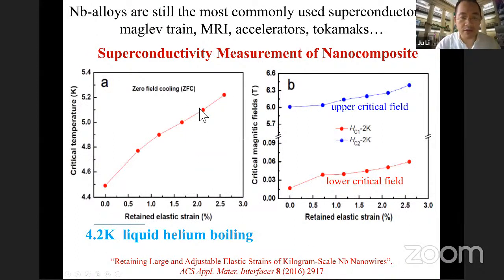And so, what it is useful for is, well, niobium alloys are actually the most commonly used superconductor in maglev trains, in magnetic resonance machines, in particle accelerators, in tokamaks. And when we adjust the wire drawing procedure, we can actually lock in this residual elastic strain on the niobium. And from our initial calculation, we predicted that the superconducting temperature would actually shift.